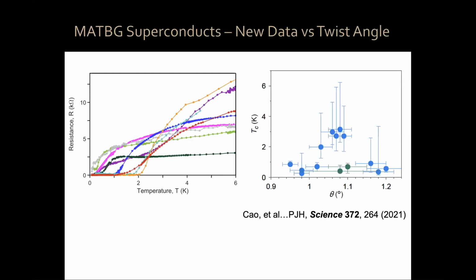Okay, so maybe a bit more on the experimental developments that have happened since April 22, which is when the paper was officially published. So the first thing is that we have reproduced our own results. Okay, that doesn't always happen, so it's good when you can reproduce yourself. By now, we've reproduced our data many times. This is actually by now very old. We have much more data, but we now have a critical temperature at optimal doping as a function of twist angle, this new knob in this matter. Okay, and you can see that indeed around 1.08, 1.09 is when the maximum Tc happens, of order 3 Kelvin. This is 3 Kelvin in a system which has a Fermi temperature many orders of magnitude lower than regular systems.